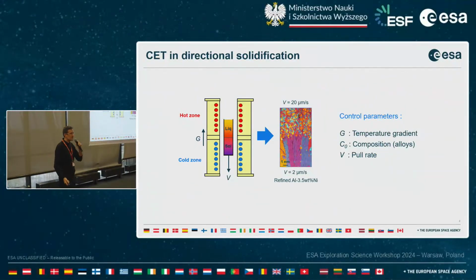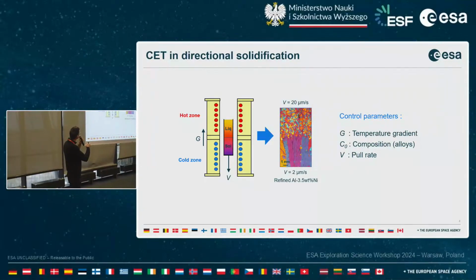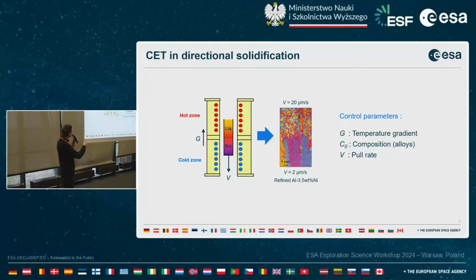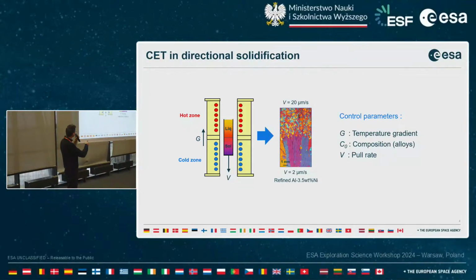And in order to simplify things, one way is to use a configuration called directional solidification that can be performed in so-called Bridgman-Stockbarger furnaces, which consist basically of putting a sample into a furnace composed of two heating zones, a hot zone and a cold zone, so that it will be partially liquid and partially solid. The main advantage of this configuration is that it allows us to control the main parameters of the solidification, which are namely the temperature gradient, the composition, and the pull rate. Solidification can be triggered either by pulling the sample into the cold zone, or you can also imagine that you can move the furnace, or you can also solidify by decreasing the temperature of the heating element.